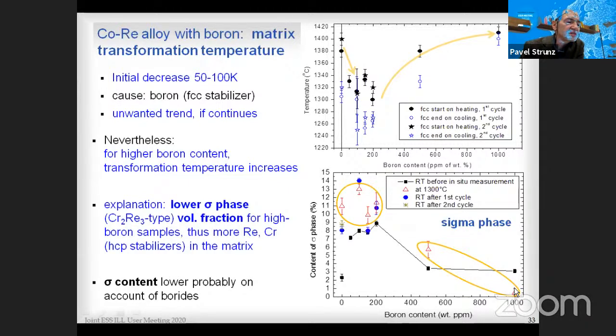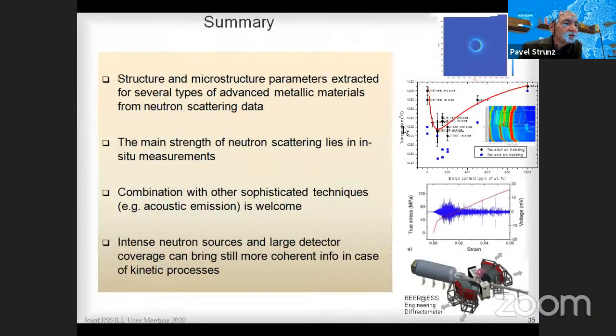And as sigma is a chromium-rhenium type phase, that means if there is a lower amount of sigma, there is a higher amount of rhenium and chromium dissolved in the matrix. And as rhenium and chromium are HCP stabilizers, this pushes the transformation temperature to higher temperatures. So it's good. And I will summarize my talk by saying that I hope I have shown that structure and microstructure parameters were extracted for some types of advanced metallic materials with a large help of neutron scattering.